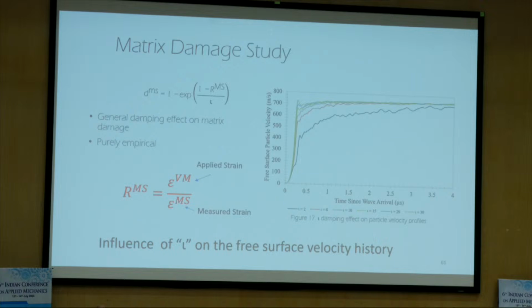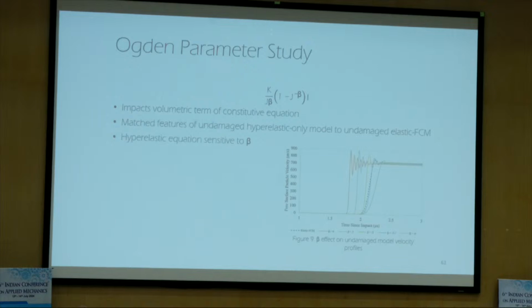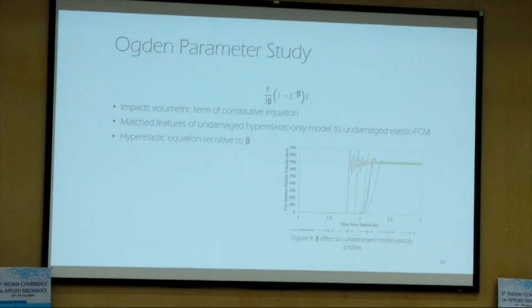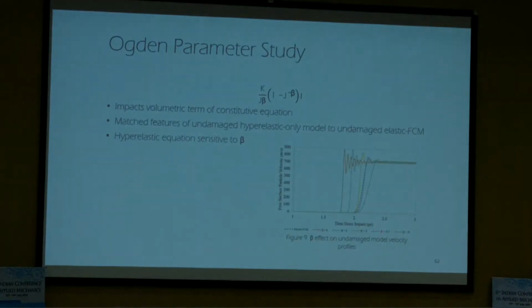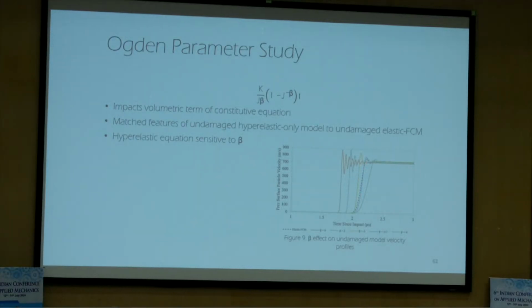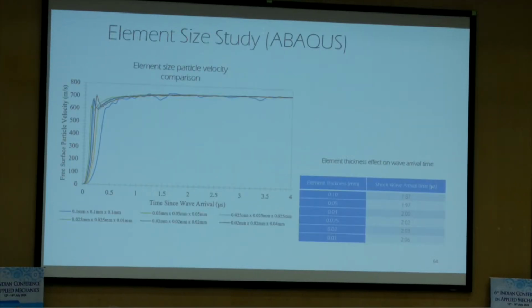That means the GRP, when the matrix cracks, develops inelastic deformation, and the iota can be used to model that. The second term, which is the Ogden parameter usually used for rubber type material, affects the free surface velocity when you change the values. So you can see you get different results, but this is the experiment. So you pick that value for that parameter, beta. The Ogden parameter, we chose -2 because that matched with the experiment. And it goes on and on.